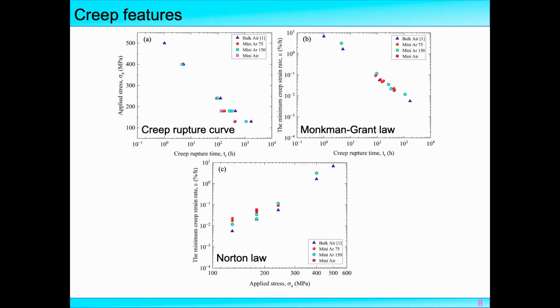From this figure, we can see that although there is a size effect on the creep rupture time, if we use the Monkman-Grant rule to predict the creep life, we can use one master curve to predict all the test conditions. And moreover, for the Norton rule, it is the relation between the applied stress and the minimum creep strain rate. So we know that the dominant factor for creep rupture time is the minimum creep strain rate. So we can see that at the same applied stress level, the minimum creep strain rates are very different because of size effect or oxidation effect.